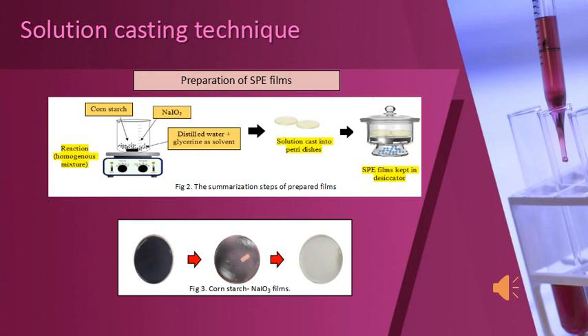For the formation of the solution, it can be observed that after dissolution of sodium iodide into the electrolyte, the solid polymer electrolyte transformed from white to dark purple. Then the SPE was left to dry naturally until it formed a thin film. The dried SPE shifted the color to pale purple, and it took 24 hours for the SPE films to finally turn colorless. And this is shown in figure 3.